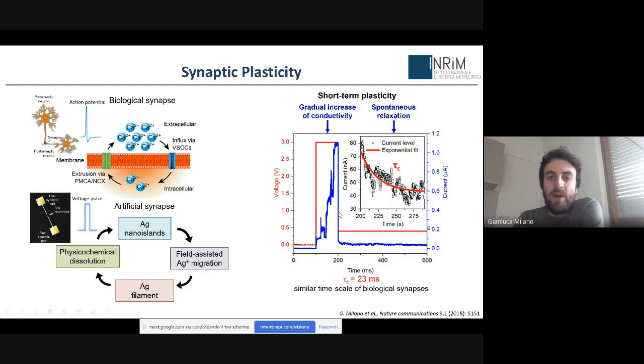So just as an example, if we apply a voltage to a memristive device, we can have a gradual increase of conductivity. This emulates the influx of calcium ions. And then after the signal, the device spontaneously relaxes to the ground state, emulating the extrusion of the calcium. And the time constant of relaxation is about 20 milliseconds. That is a similar time scale to biological synapses. So just by properly tuning the operational conditions, we can reach some analogy to biological synapses in memristive devices, also in terms of time scale of synaptic processes.